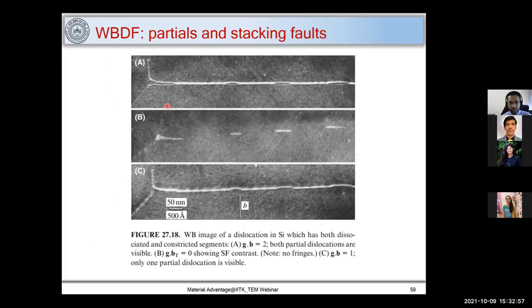Now this is a classic case which I would like to discuss when you talk about weak beam dark field imaging, imaging partials and stacking faults. In the first case, you have G dot b not equal to 0. So in this case, both partials will be visible, because for G dot b equal to 0, the dislocations will be invisible. In this case, I do G dot b equal to 0, and I can see only stacking faults with these two partials. I don't have these partials which are left here. And if G dot b is equal to 1, I can have only one partial which is visible. So using the proper G dot b condition, you can find out whether there are partials or stacking faults in between.